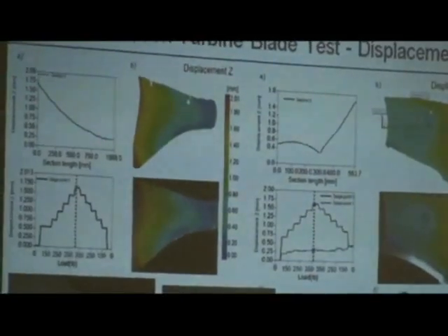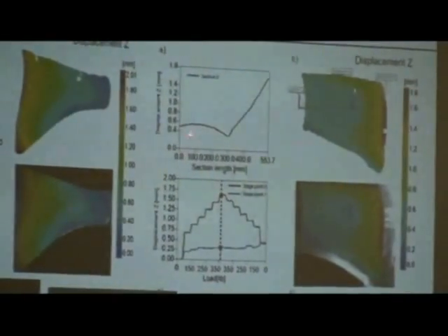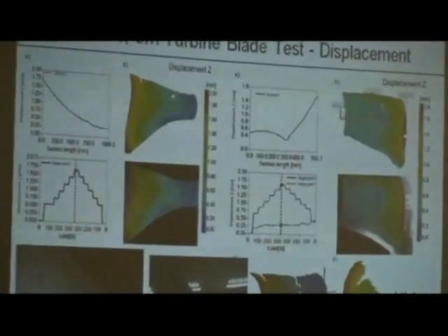What we're showing here is the deflection at 400 pounds, and then on the underside. This is the top side, this is the bottom side. On the bottom side, there was a crack located right about here, and just by looking at it, you couldn't tell that there was a significant change. But by using this technique at about 400 pounds, we have a huge discontinuity in the shape of that structure. And so let's take a look at the video of that as well.